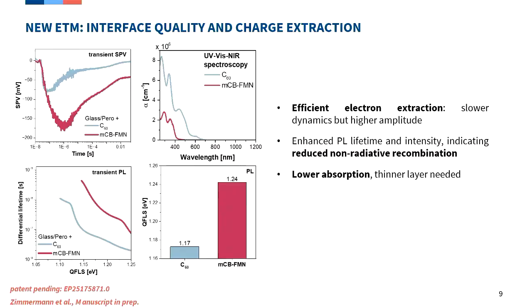In your transient, you want a strong signal - meaning strong separation by itself - and you want it to be very quick, and in the right direction, so charges go the right way. Comparing C60 and the new molecule, charge separation is a bit stronger by itself. However, if you zoom into the early time of the transient, the rise time is a bit smaller, and that has a reason I'm coming to in a bit.